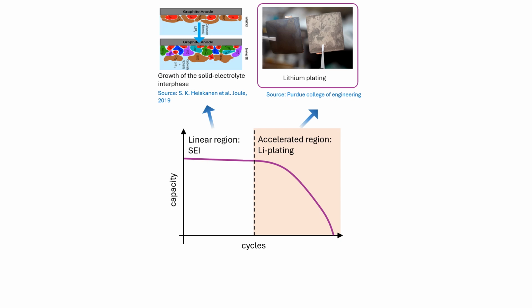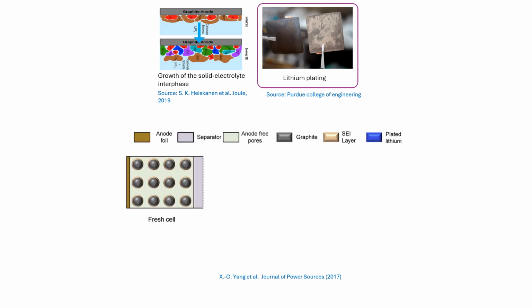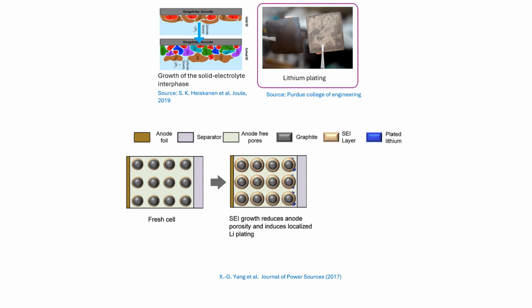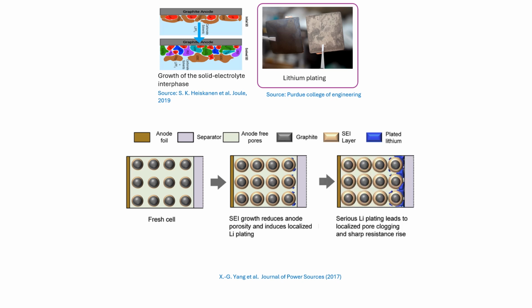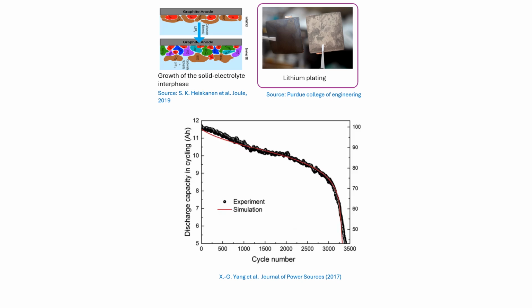This transition process can be summarized by the diagram below. This is a fresh battery cell. As the cell is charged and discharged, the SEI layer is formed and grows thicker, reducing the anode porosity. This process will induce localized lithium plating. At high cycle numbers, lithium plating will accumulate, which leads to localized pore clogging and sharp resistance rise. This is when the battery degradation really starts to take off. An analytical model can be established by considering SEI formation, lithium plating, and other related parameters to predict battery cycle life.